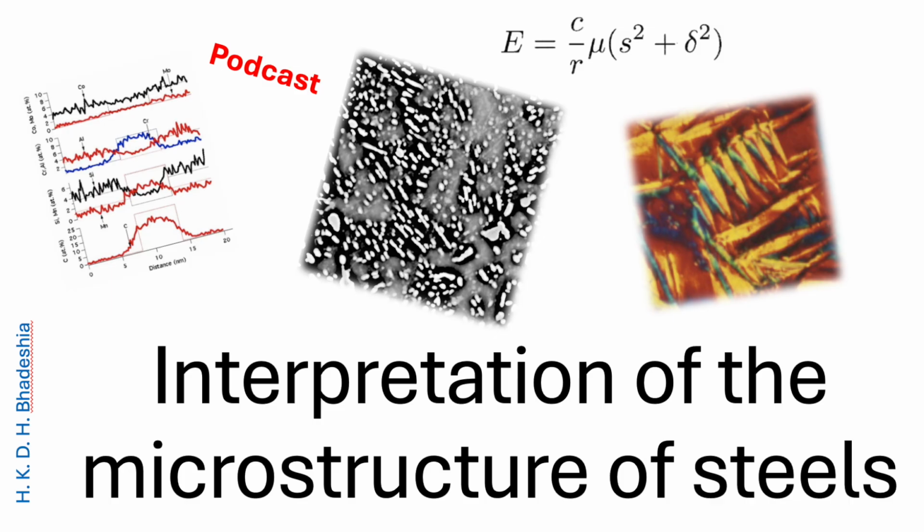Yeah. Thermal grooving is the standard. You polish the sample and hold it at the austenitization temperature. Surface tension then naturally carves grooves along the prior austenite grain boundaries. So you can see where they used to be. And you can measure the original grain size, which, even in a displacive structure, remains critically important for performance.